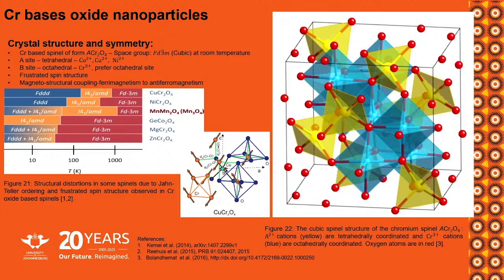You go from a ferrimagnet, almost ferro, alignment of spins, same direction, antiferro in other cases. The big thing about that is that you can actually find 2 different magnetisms around the transition point. And we actually had one. This is one of my first masters that I supervised. So in this case, the student used copper and nickel. They're what's called Jahn-Teller active, meaning in some of the orbitals you've got a split in the energy gap or energy band.